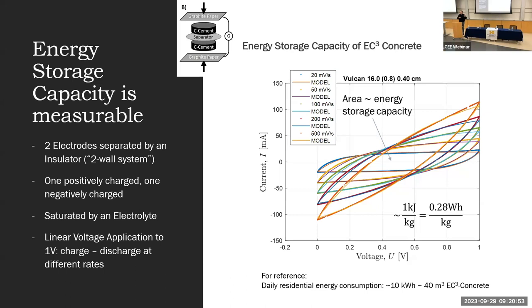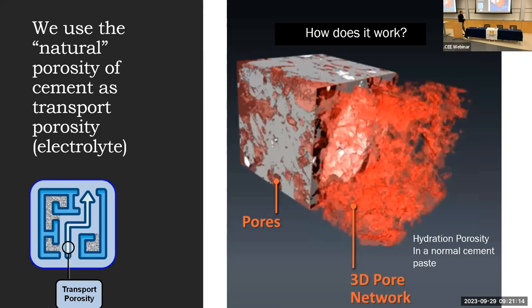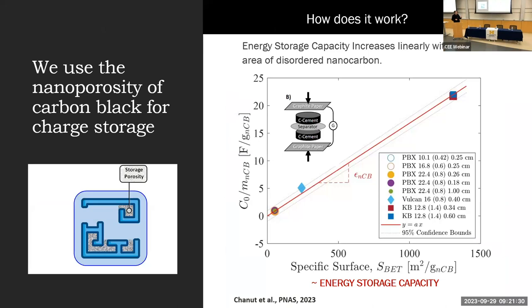And if we scale this with the cement paste in concrete, we would need on the order of 40 cubic meters of this type of concrete for the daily consumption of 10 kilowatt hours of a home. So from that point of view, we make use here of this porosity, the 3D porous network in cement-based materials for the electrolyte. And we use it as the transport porosity, and we use the carbon black as storage porosity.